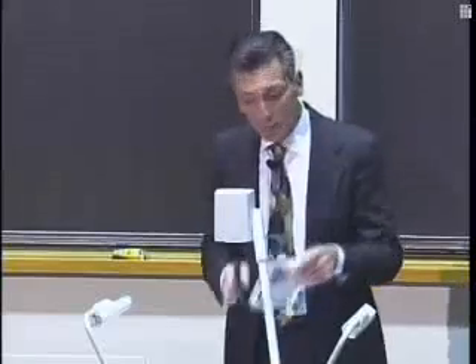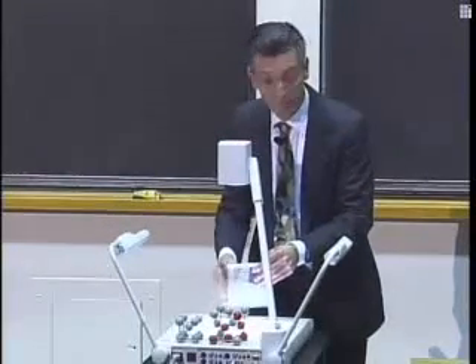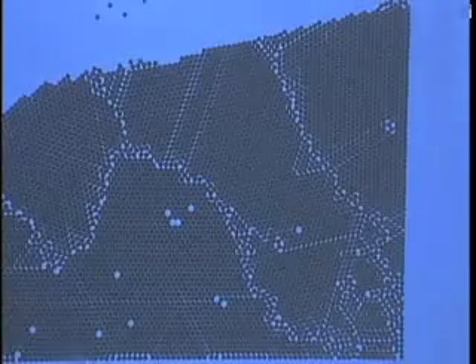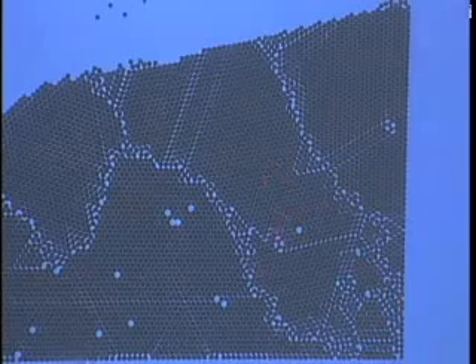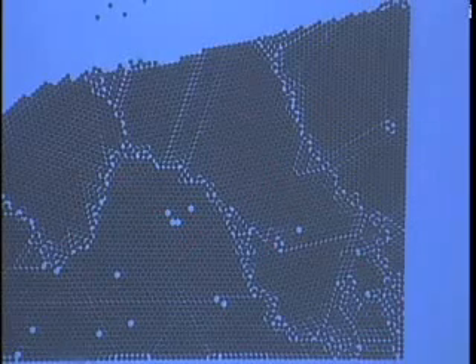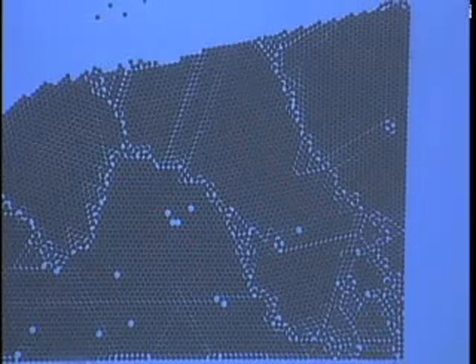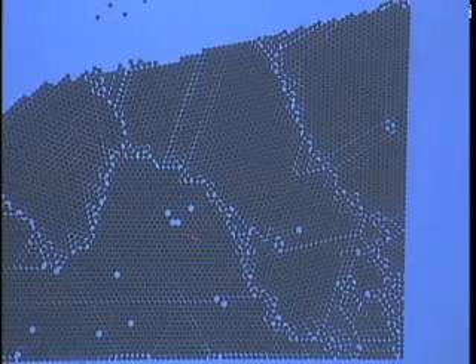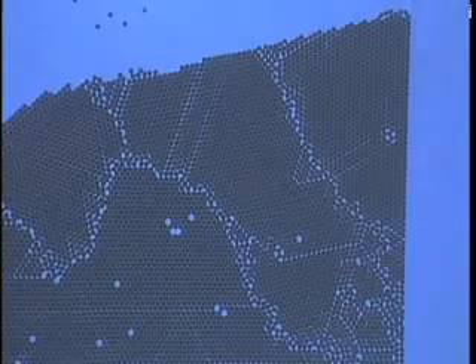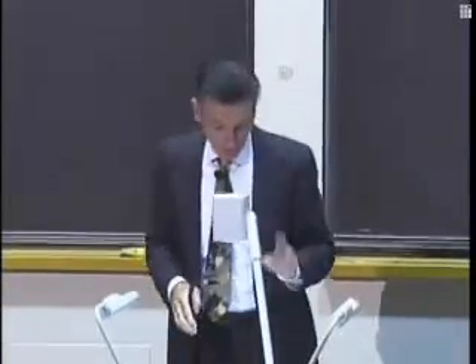Okay, so now what I'm going to do is I'm going to anneal. So I'm going to lift this up, and annealing would be the equivalent of tapping this. Okay, I'm giving thermal energy to this because thermal energy causes atom motion. Look at the impact. I have annealed out so much of the defects, and now look at large regular regions. There's the surface. Hey, see a few gas atoms up there. And look, vacancies. There will always be vacancies above 0 Kelvin.